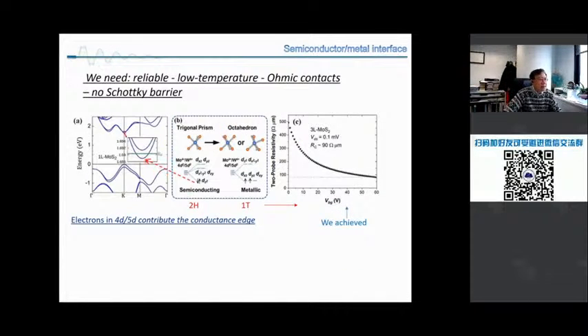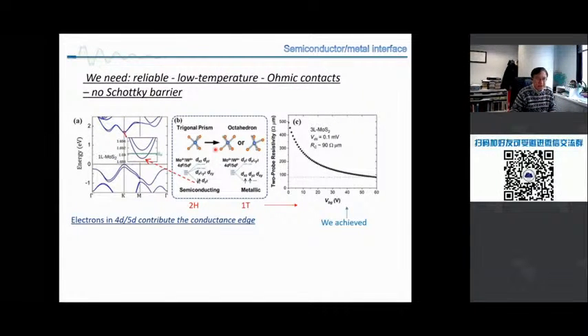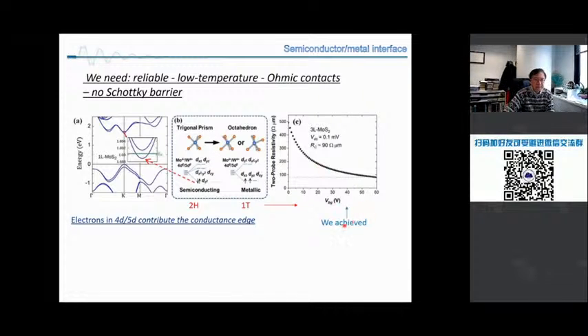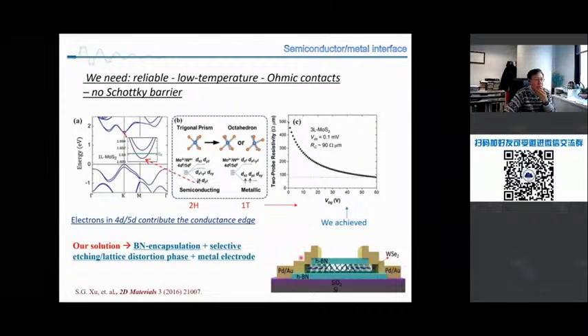So if you look at the details of the bands, the minimum band in the conduction band here, for example, if it's a 2H phase, the lowest state is the d z squared. I mean, there are two states, spin up, spin down, occupied by electrons, and then there are no extra electrons, and that's the reason that they have a semiconducting 2H phase. But if you make a distortion, the minimum states actually are partially occupied, and that's the reason you see a metallic phase. All right, and if you make such junctions, from the lattice structure or bonding point of view, it's similar. That's the idea. Now, in it, we make such a connection and achieve very low contact resistance, for example, for 3-layer molybdenum disulfide channels. So our approach is based on this.